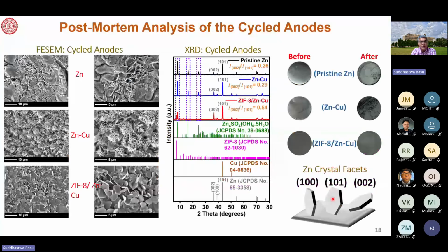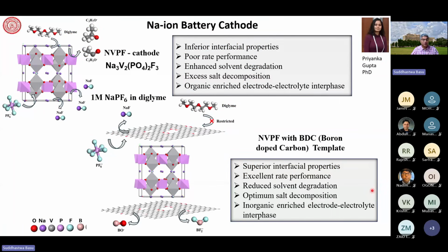And then we did a post-mortem analysis of the cycled material. As I showed you, there was a thin film of ZIF8 which prohibits the growth of dendrite in the vertical direction but allows it to grow in the horizontal direction, and that's how you see the FESEM of the cycled anode as you move from zinc to zinc copper to ZIF8 zinc copper. And when you go to ZIF8 zinc copper, you have this slanted growth, and the growth is diverted toward the slanted side, not towards the upward direction, which would then pierce through the polypropylene separator and go to the cathode. That is what you don't want. Okay, so this is the mechanism we are showing you, and that's about the zinc battery.